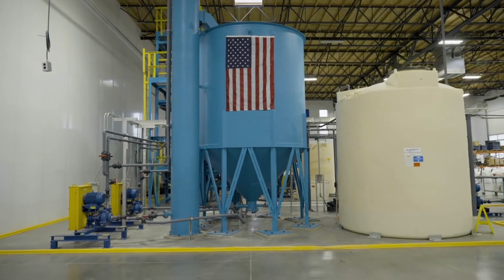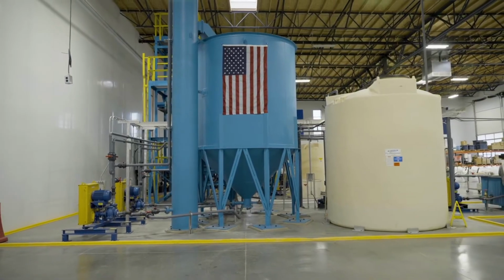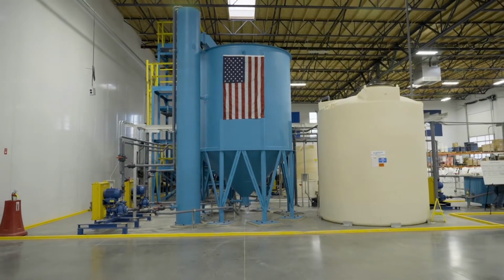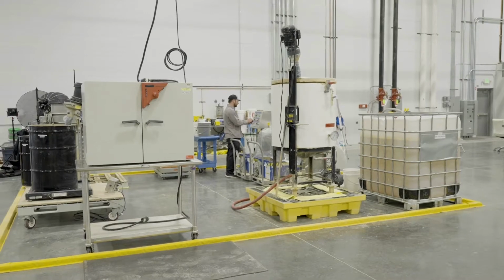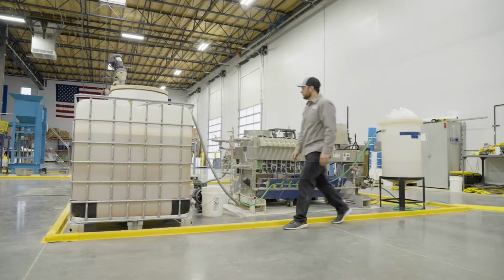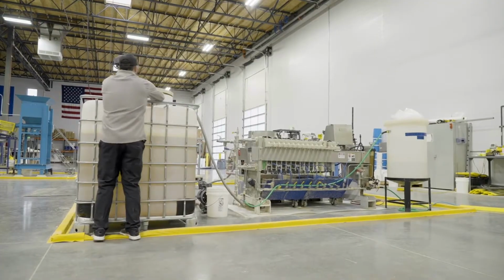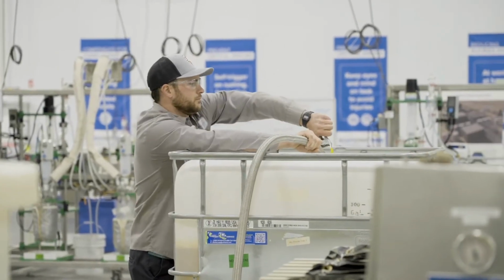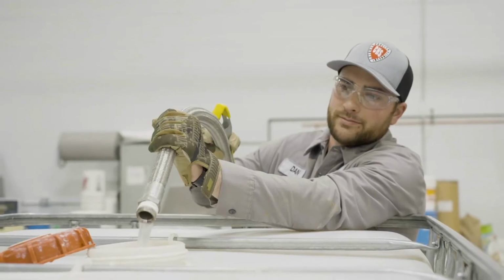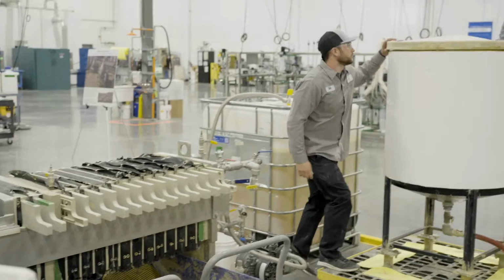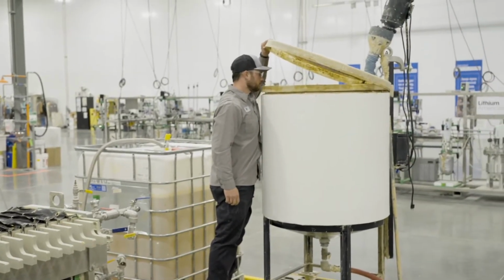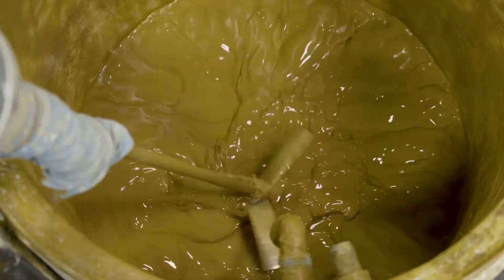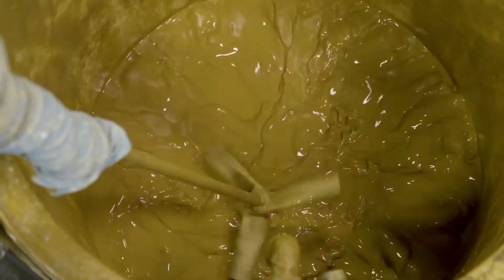After leaching, there's some residual acid. We neutralize with limestone and subsequently raise to a completely neutral pH with magnesium hydroxide that is recycled from downstream in the process. This slurry that is then neutral, we put through countercurrent decantation. This is a washing process where we have a 99% wash efficiency, removing all the lithium and other elements that have been leached. These feed downstream to the purification section of the plant.